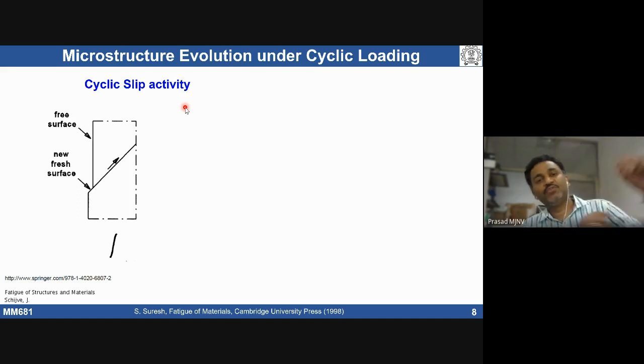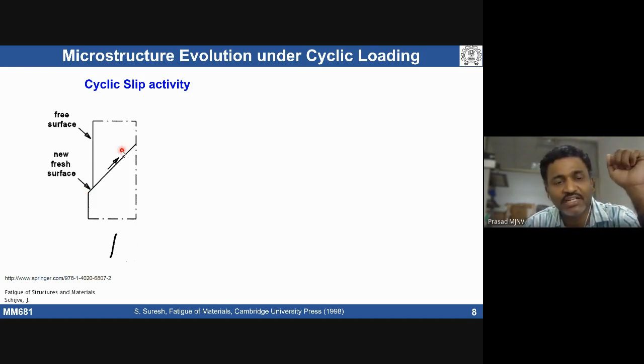When I deform a material plastically, assume that I'm deforming it below yield stress, at certain locations the stress can rise locally, which can lead to plastic deformation. When there is plastic deformation, that means there is shearing activity taking place. So at the surface, we take a single crystal. If I deform it around the loading direction, now I applied a stress to maximum peak stress. Plastic deformation basically involves shearing activity. So this shearing activity at the free surface is going to generate some new fresh surface.